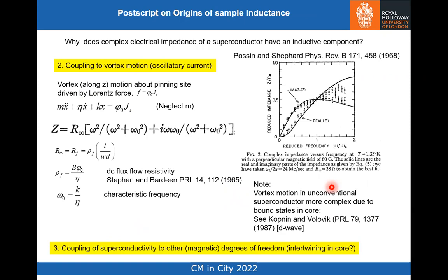Another possible origin is, again, actually, this was pointed out in a conversation with Seamus when we saw this apparent transition at TA by another method several years ago. He said, well, for goodness sake, you need to measure the complex impedance, which is what we did. The change in the vortex structure between one phase and another would potentially be reflected in that, because vortex motion contributes to sample inductance.